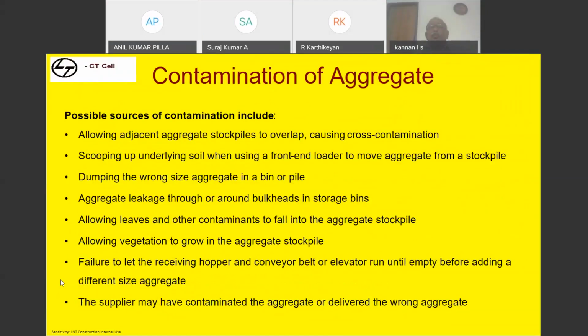Then, possible sources of contamination: what can happen at the batching plant? Allowing adjacent stockpiles. If you are dumping aggregates side by side, 20 mm, 10 mm or sand, and there is no bifurcation available, there is a possibility of overlapping, which can contaminate the aggregate. When the contaminated aggregate is fed again, your mix design parameters will change, and your concrete quality is going to change. The same as I said, scooping underlying layers of soil using a front end loader, already discussed.